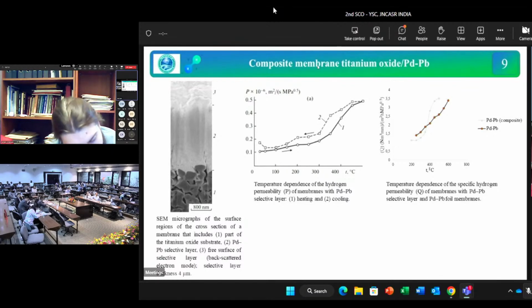The porous titanium oxide was used as the substrate. The function layer was deposited by magnetron sputtering. The figure shows an image of a portion of the transverse section of the composite membrane. The performance of the membrane for a heating-cooling cycle and specific hydrogen permeability is given in comparison with that of the membrane manufactured from the palladium-lead alloy.